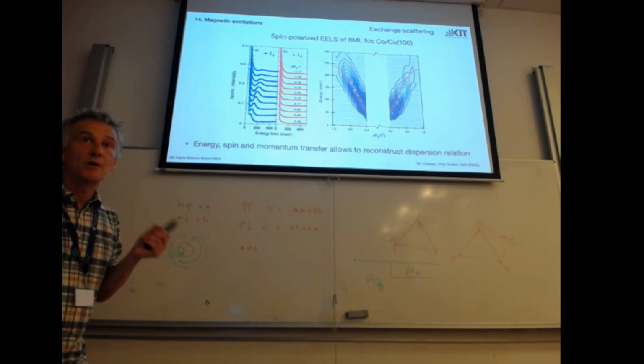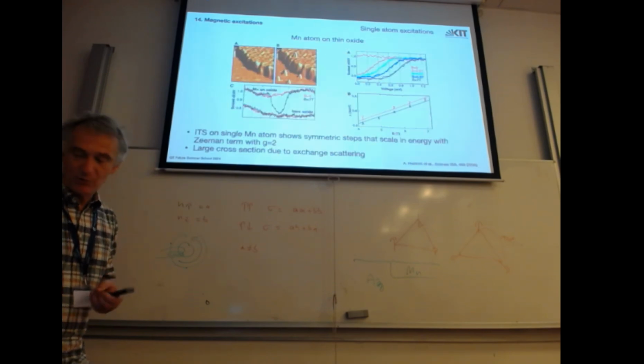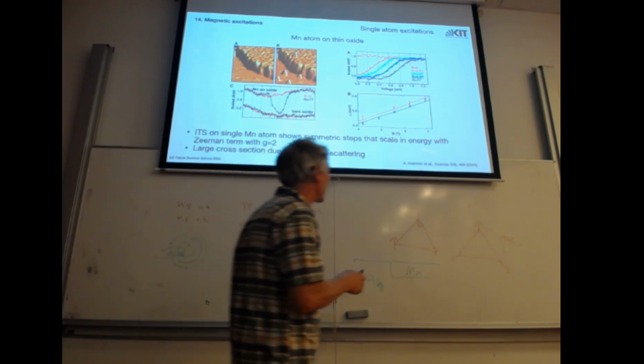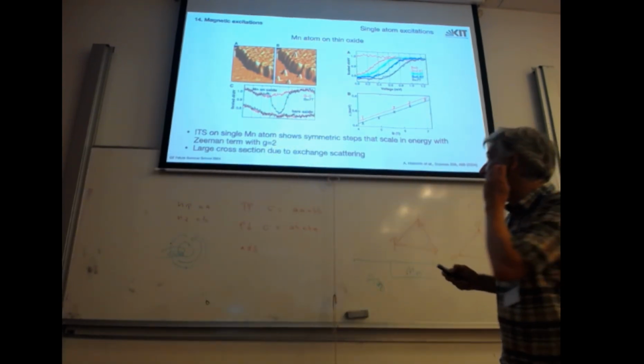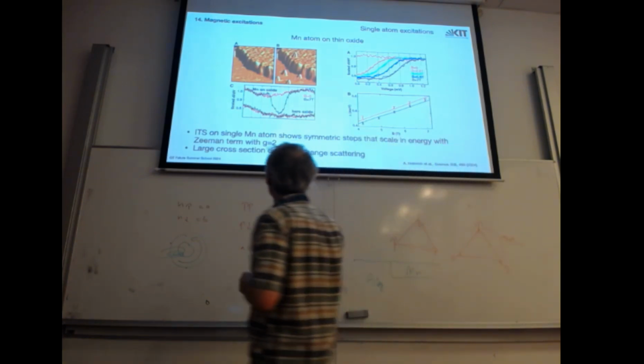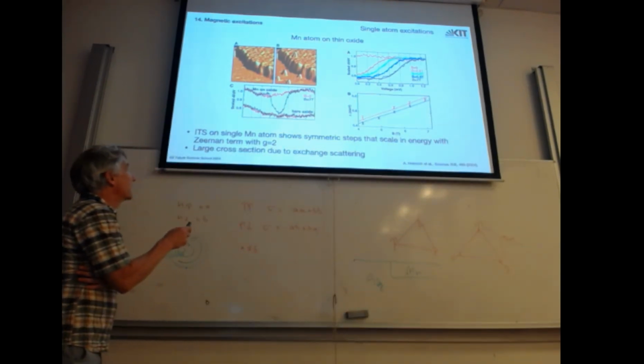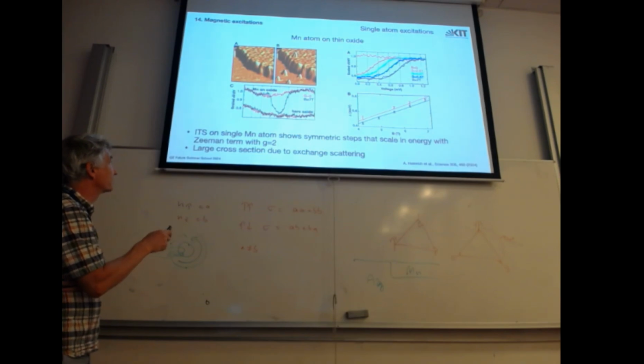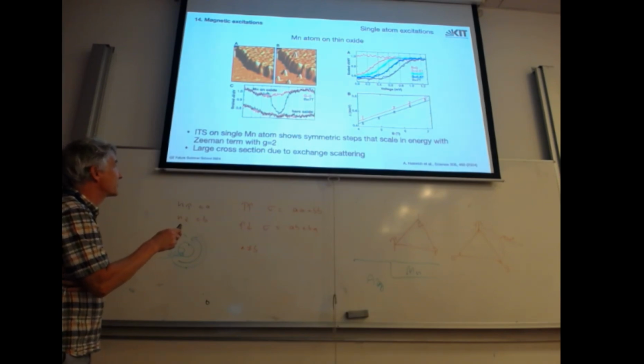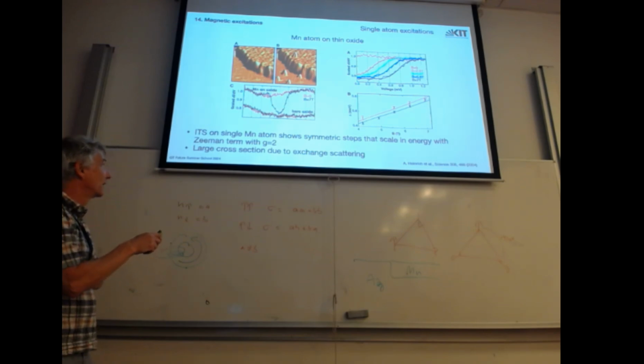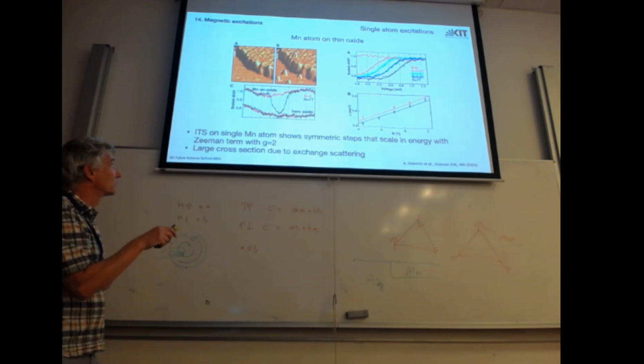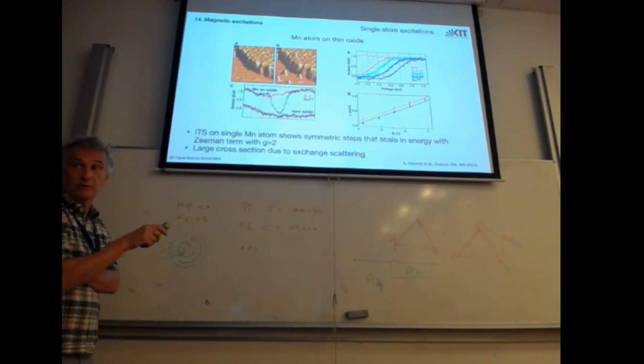So can this be done also in STM? And I worked on that and we were overtaken by Andreas Heinrich at that time. He did a very nice experiment. Manganese atoms on a thin oxide. So this manganese atom sits on an oxide layer. This is a substrate. And on the bare oxide, you see the IV is flat, and on the manganese atom at B equals 0 it is flat.